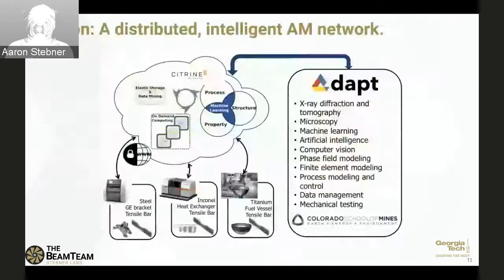And the big goal here was the industry academic partnership. If we had different companies in the center, each with different printers printing different materials, and they would send into the center generic things like tensile bars or compression samples that they printed alongside their other parts, we could build up this non-proprietary database around the quality of all these generic coupons, and build these models. And then when company A wanted to enter titanium, they could draw from company C's data set on titanium and lower the bar for getting qualified. That was the big goal.